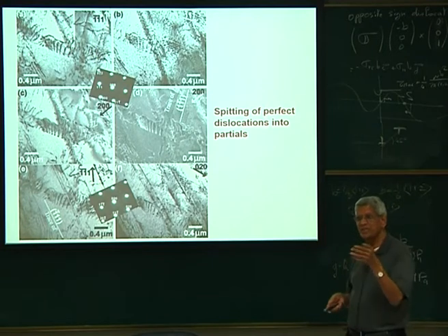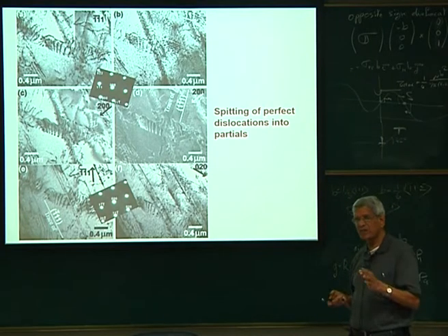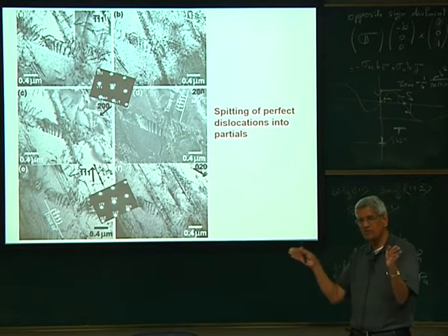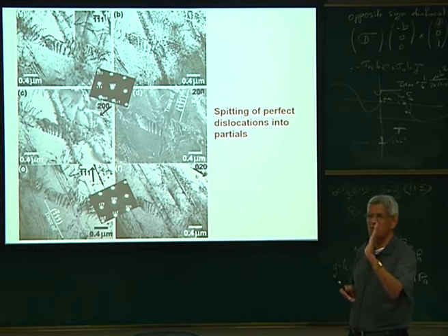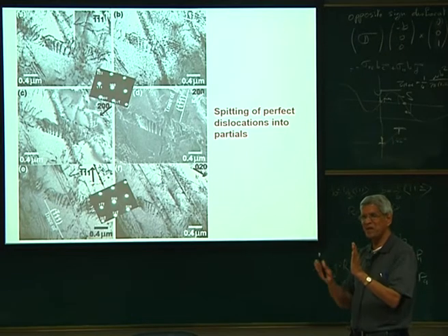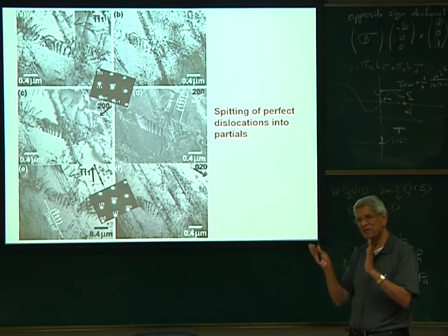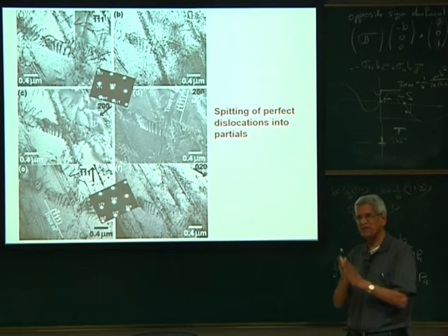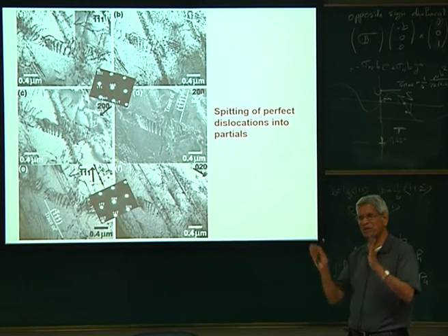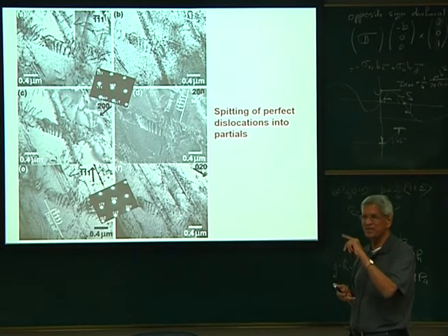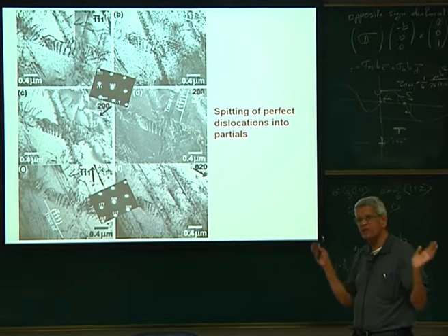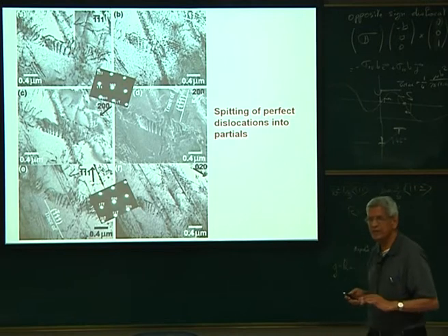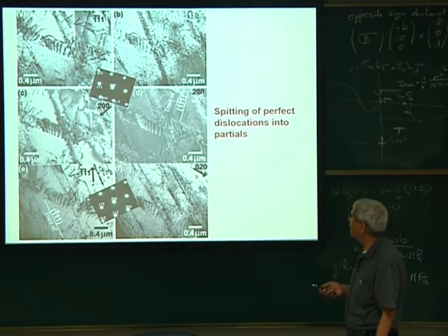So under different imaging conditions, for a stacking fault, in some conditions only the fringe will be visible and the dislocations could become invisible. Under some conditions, the fringe and one partial could be visible. In some conditions, the other partial and the fringe could be visible. In some conditions, both the partials and the fringe could be visible. There are some conditions where only the partials are visible. That's the one which I had shown yesterday for analysis of the dislocation using computer simulation, where the fault has become completely invisible, correct? So all these possibilities are there.